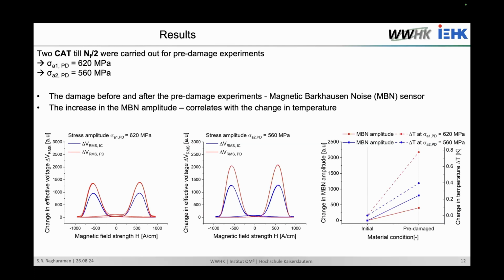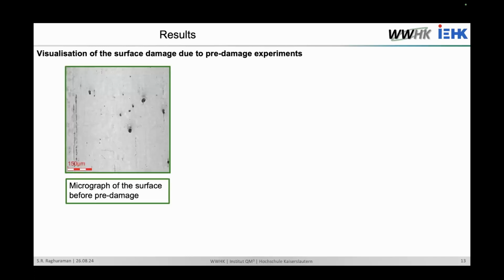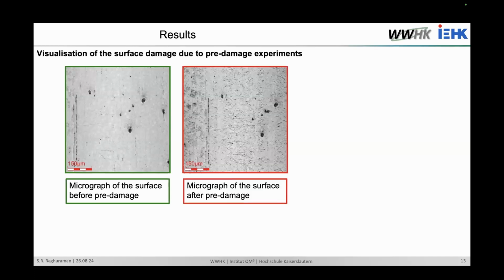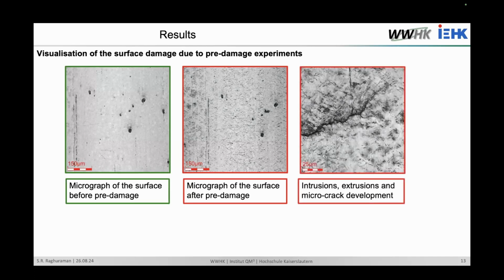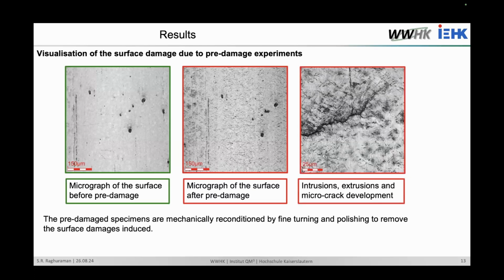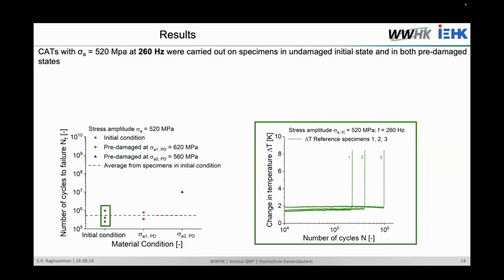And this is also reflected in the temperature curves. This is the initial stage, and this is the pre-damage stage, and both show an increase, a proportional correlation. Next, we also did microscope investigations to visualize the surface damage. This is the surface before pre-damage in the initial condition. This is the surface after pre-damage, and we also noticed some microcracks developing. After these pre-damage experiments, we removed the surface damage that we had introduced mechanically by fine turning and polishing. So now we are done with the pre-damage experiments.